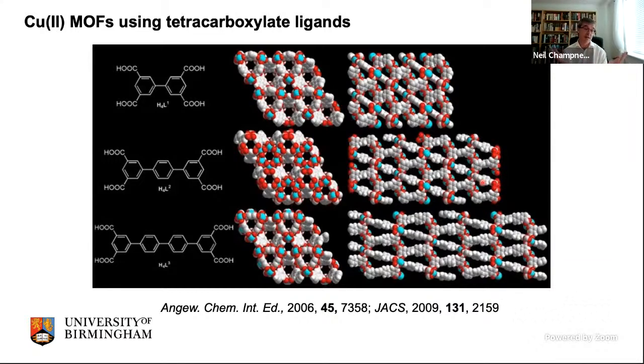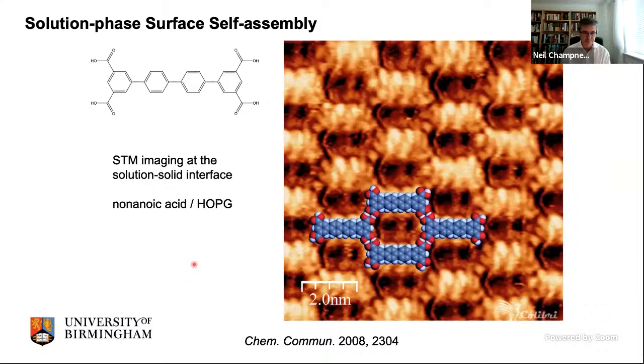The first one is telling you that we had a whole series of carboxylic acids available to us anyway from other chemistry we were doing. And the other thing is that we can actually change the structure of these really quite simply. You can make them longer and longer and longer as you see fit. And then you can start to look at the surface self-assembly of those systems. That is what we thought: carboxylic acids, hydrogen bonds, so why not? So we started with this system here.